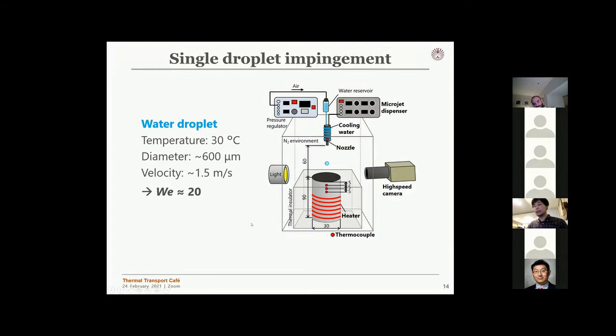We've done a secondary experiment on single droplet impingement. This is the setup: a cylinder of stainless steel with embedded thermocouples, heated using a heater. We have a tiny nozzle called a microjet dispenser, which can eject one single droplet, allowing us to precisely control the diameter, velocity, and temperature of the droplet, so we can focus on one single droplet as the fundamental process of spray cooling.